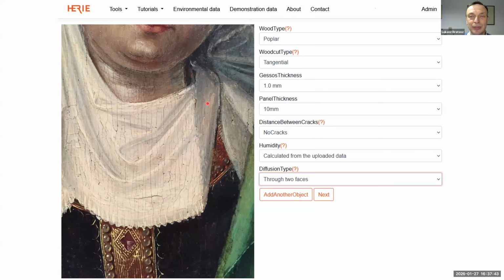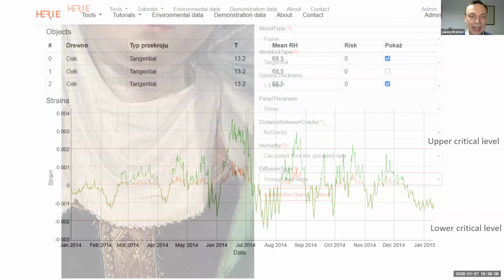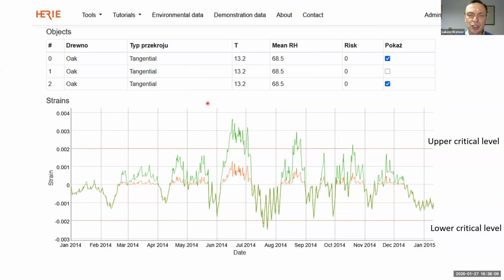You can select the type of the cut of the wood, tangential, radial, and gesso thickness. Gesso in this case represents the paint layer. There will also be an option to select different panel thicknesses for the panels, and distance between cracks. Also the humidity, the type of how humidity is calculated, and the type of the diffusion. So as a result, you obtain some numbers, but these numbers are expressed in terms of strain, but there is a long way between strain and actual loss of the value of the cultural object.